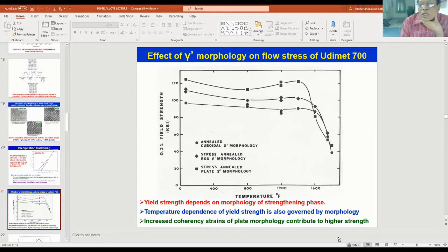You can see that generally what we expect is, for example, steels, if you take mild steel, strength falls down very rapidly with increasing temperature. But in case of nickel-based superalloys, you see the strength is maintained up to very high temperatures because of several strengthening mechanisms that are operating. But when you change the shape of your gamma prime precipitate, you see that strength is increasing. That secondary hardening is coming here. You see that at elevated temperatures, strength is getting increased.